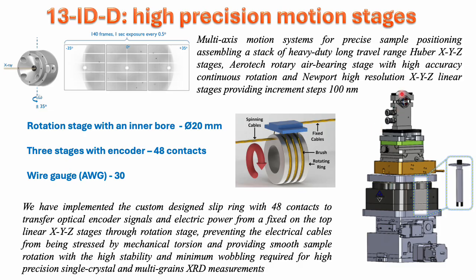We have upgraded our sample stage stack, adding an Aerotech rotary air bearing stage for high accuracy continuous rotation, and also introducing a slip ring, where all the wires from the top stages come through the rotation stage without leaving any cables, so that our rotation is very stable, with no wobbling.